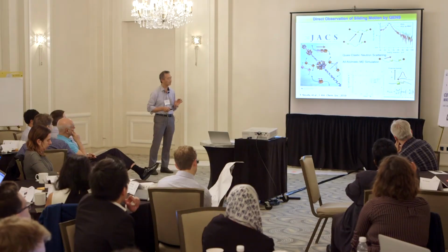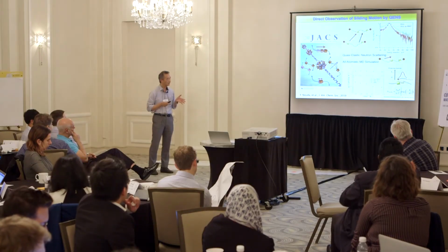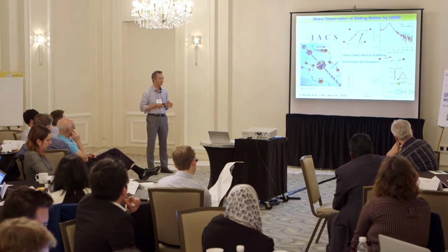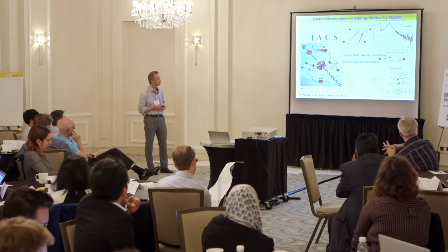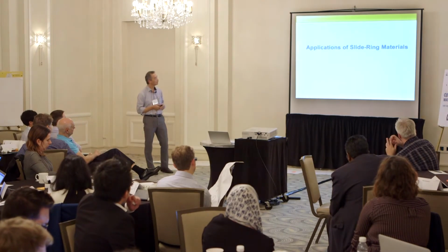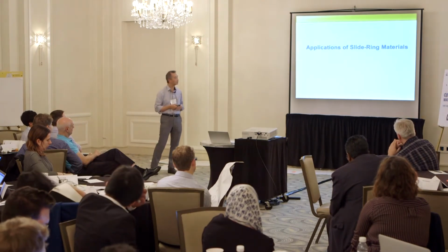Recently, we directly measured the sliding motion by using the quasi-elastic neutron scattering technique. This sliding speed is almost the same as the value we estimated from the fracture energy measurement. Okay. So next, let me show you some applications of Slide-Ring Materials.